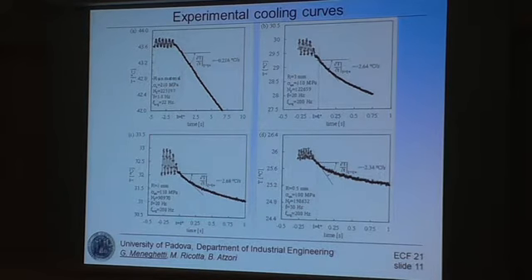You can see here different examples of cooling curves. You can see here an example from a smooth specimen. You can see that the heat production was very high, so the thermal gradient is rather constant for a quite long time window, so the thermal gradient could be measured very easily. You can see, for example, for the case of a much sharper notch, with a radius of 0.5 millimeter, that the time window useful to estimate the thermal gradient was much shorter. You see also that the thermal gradient was quite low in this case and was much higher in this case. So this is a typical experimental situation that can be seen when applying this approach.